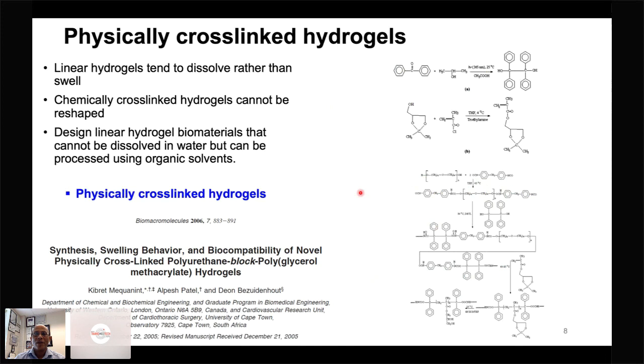And if you then use chemical cross-linking agents, you can transform the linear polymer into a 3-dimensional polymer. But then the chemically cross-linked hydrogels cannot be reshaped. Which means if you want to redissolve it or form a tube, if you want to go into a slab form, then you cannot really do that, because once those cross-links are formed, then they are permanent. One can use heat treatment to see if you can soften the material and reshape it. But oftentimes the temperature is high enough that you degrade the hydrogel rather than softening it to reshape it. So this option was not an attractive option for us.